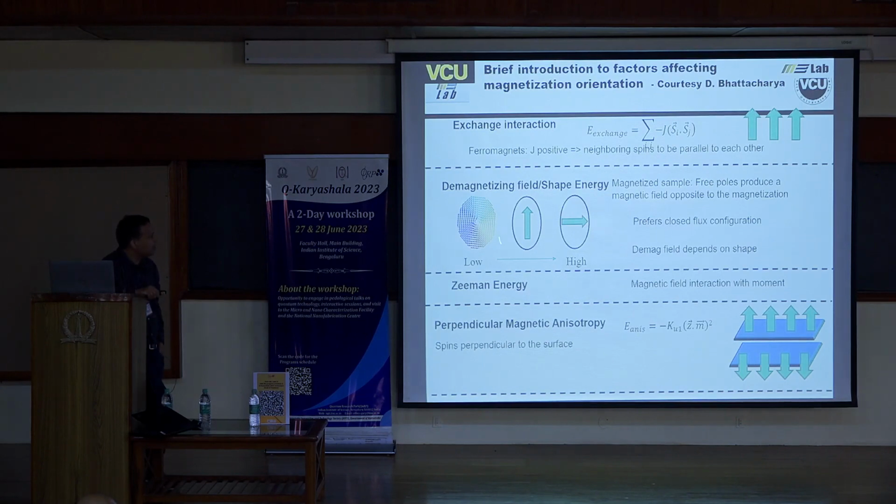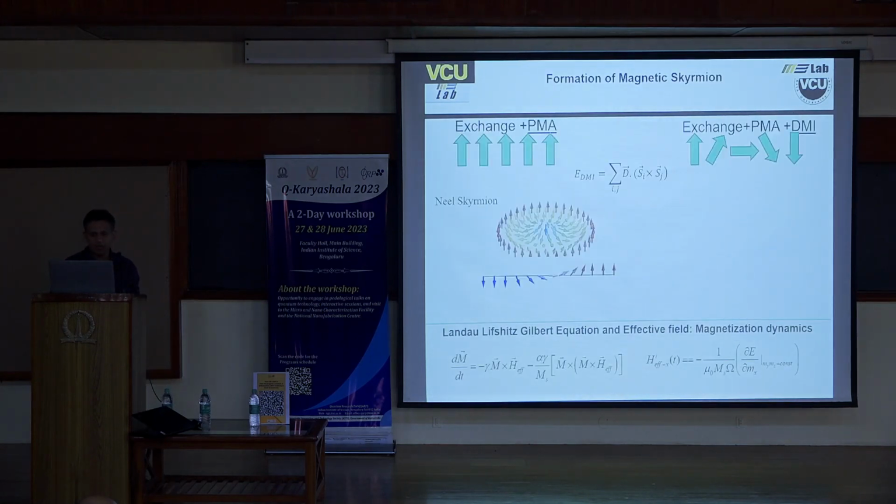What about if you make this bigger? This is probably true for 100 nanometers. If I go to a micron, then those spins can all rotate like this ever so slightly, right, and form a vortex, but they are not strictly parallel. They have enough atomic lattices to perform this rotation that are almost parallel to each other, and therefore a nice ring or vortex state may be the most stable. And it goes on, but this gives you all the terms.